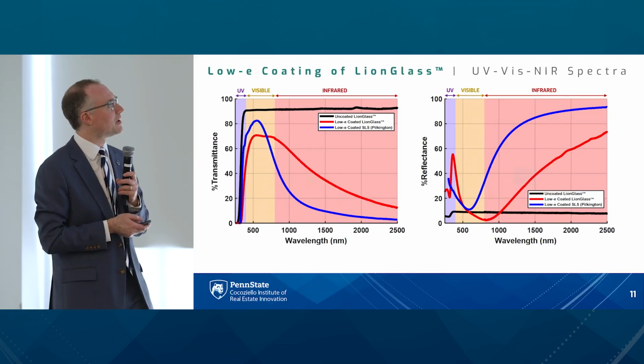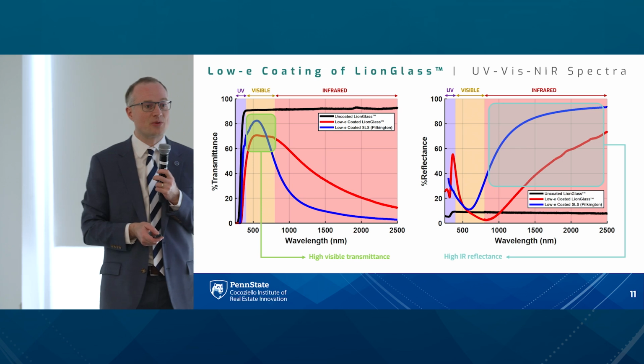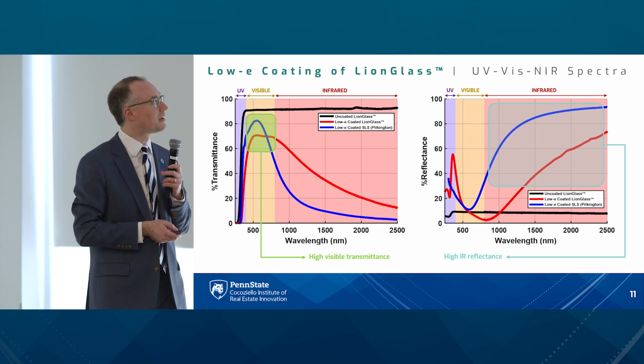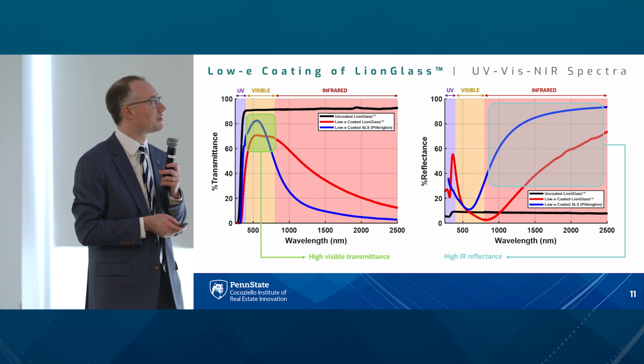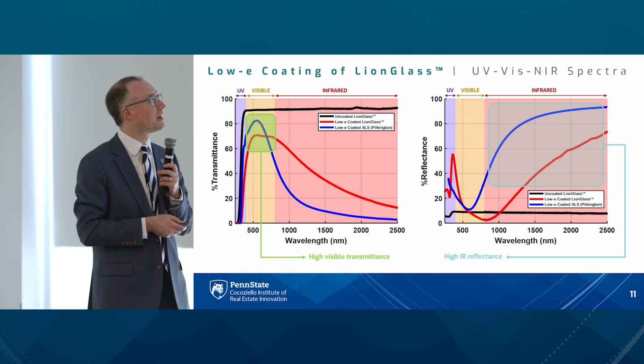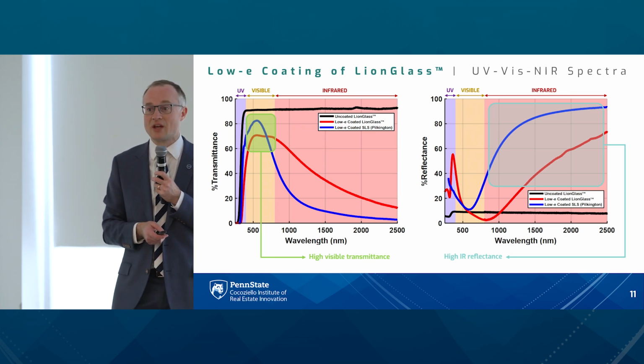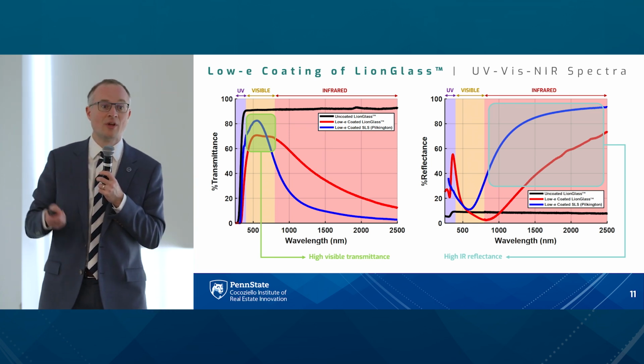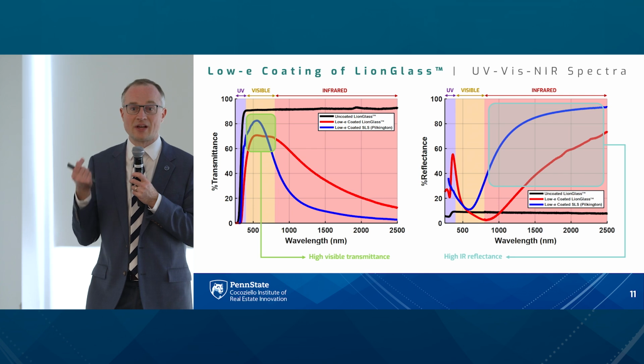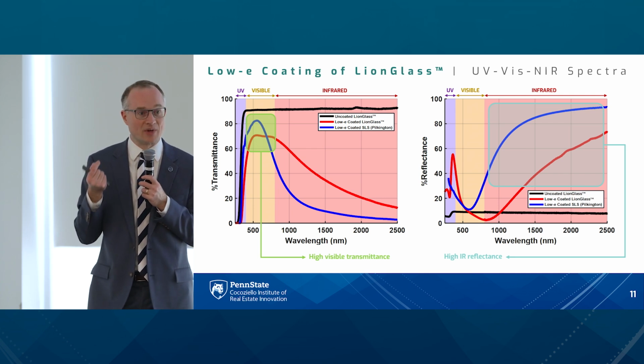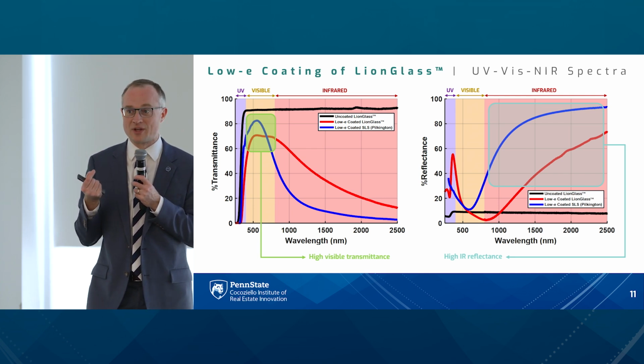Optically, it is also looking great. On the left, you see the percent transmittance of Lion Glass versus soda lime. The uncoated Lion Glass is shown in black. You can see the excellent transmission across the spectrum. One of the other nice features of Lion Glass is that it does not have that same greenish tint that standard soda lime silicate glass has.